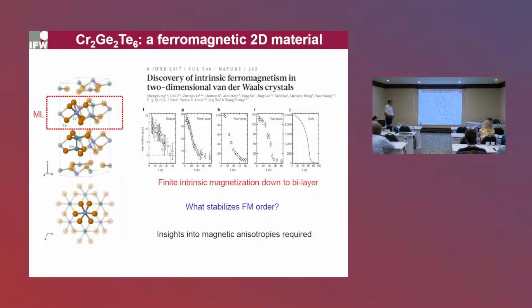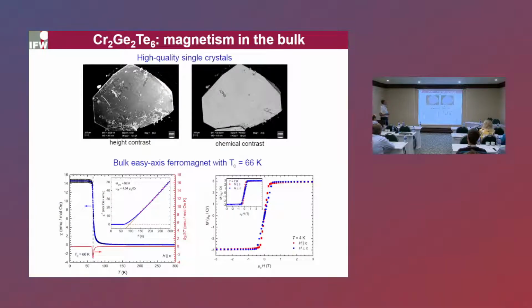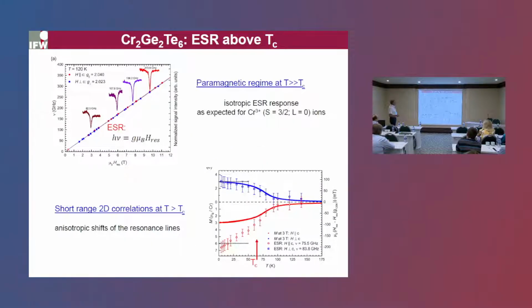And then there's a very important question: what stabilizes the ferromagnetic order in this material? Insights on magnetic anisotropy were required, and so we attempted to obtain them in our measurements. For that, we have grown high-quality single crystals of this material, which are very flat and very chemically homogeneous, and we could confirm that in the magnetization measurement they show a clear-cut transition to the ferromagnetically ordered state with a Curie temperature of 66 Kelvin. And the magnetization curves are very similar for the in-plane and out-of-plane direction, suggesting that it's a very soft ferromagnet.